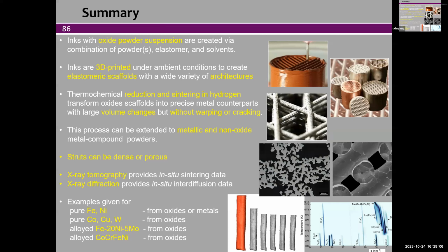By the time we have particles, it's more viscous, the pressure increases, and often we have clogging if we have agglomeration of particles. So if your particles are sub-micron, like we're using, that's number one, and more importantly, if they don't coalesce into agglomerates that may be larger, we are able to extrude down to 50 micron, which after sintering, now that's the shrinkage that helps us, right? It goes down to 25 micron. So it goes from 50 as extruded to maybe 25. Much below that is probably not possible.